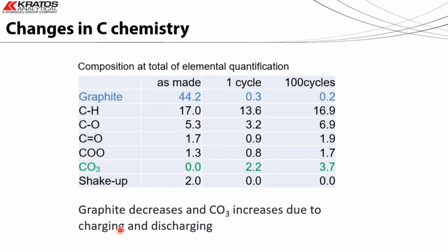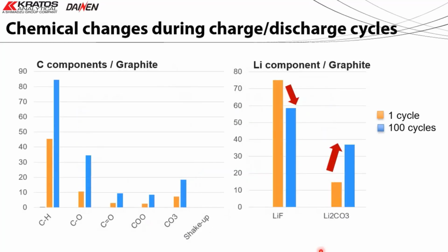So the graphite decreases. I guess we're attenuating the graphitic layer with our SEI layer, which is growing as a consequence of the cycles. If we plot the same data on a bar chart, here we're plotting the relative change relative to the graphitic carbon for the first cycle and the 100 cycle sample. So we can see the build-up of both the organic degradation products and this carbonate layer.